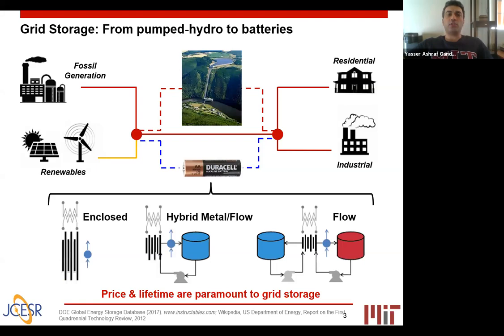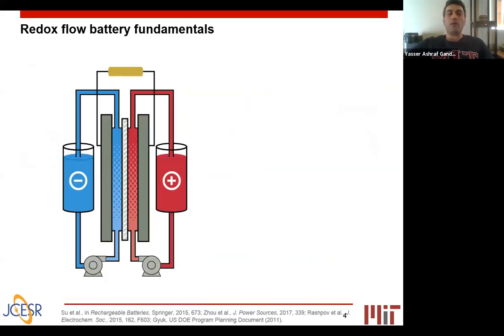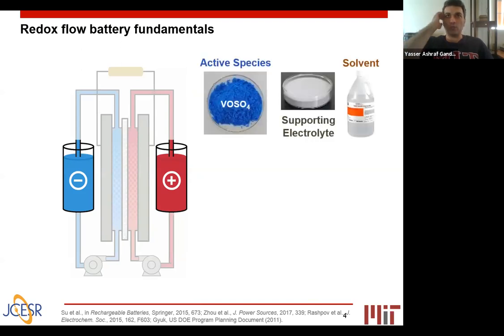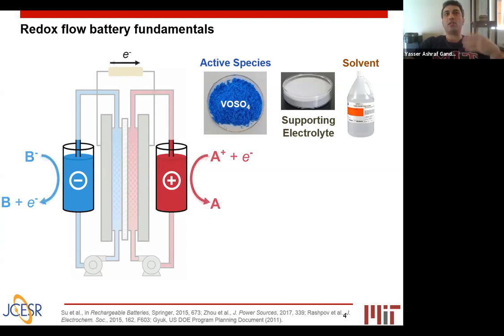Among these technologies, we are interested in electrochemical-based systems, including enclosed, hybrid metal flow batteries, and conventional flow batteries. I'm showing you here a conventional flow battery where we store the energy externally to the reactor within the low potential and high potential electrolytes that can include organic or inorganic active materials, supporting electrolytes and solvent. When we run the cell, the state of charge of the battery comes down, then we flip the polarities and start charging. This process can happen indefinitely as long as our electrolytes or reactors don't degrade.